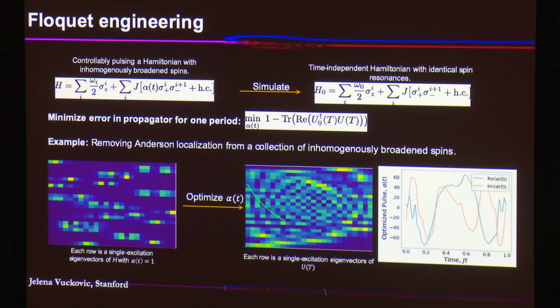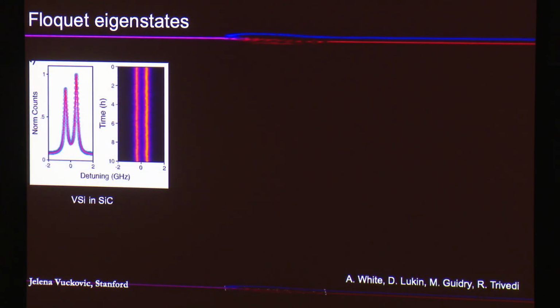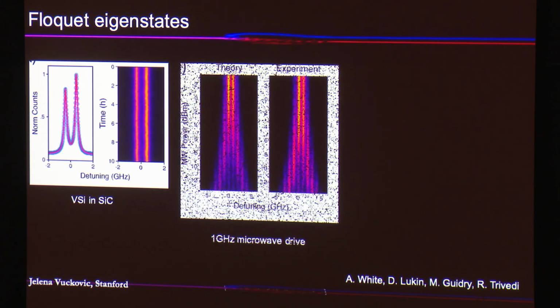So I'll just show you some preliminary results which show that in the system where you have different kind of broadened spins, you will see some Anderson localization, right? It doesn't look very uniform. Your field would localize at specific spots, and you will not really have spin-spin interaction between different ends of the array. But when you optimize driving on the system, you can remove a lot of that, remove that localization. And that's simply by optimizing optical driving on the system. And we're working on that experimentally, but as the first step, we're showing that this pulse driving actually on color centers in silicon carbide can really lead to the right type of spectrum.